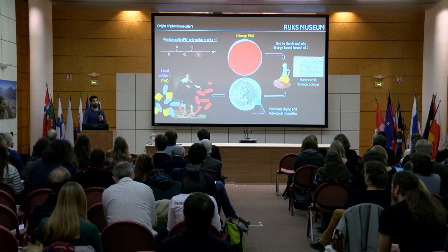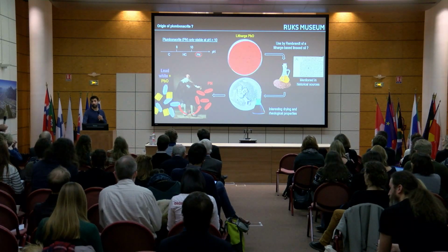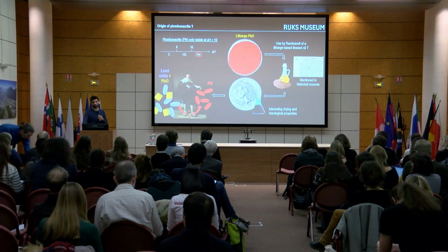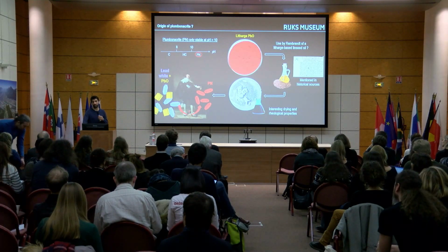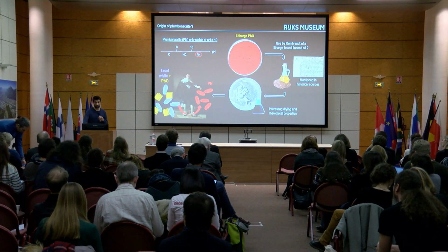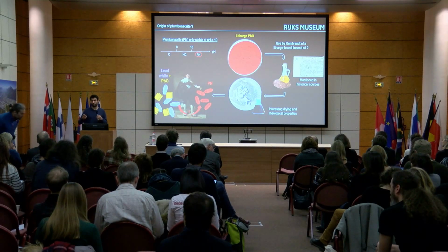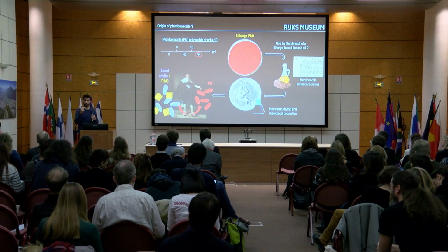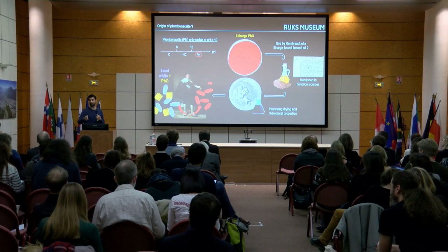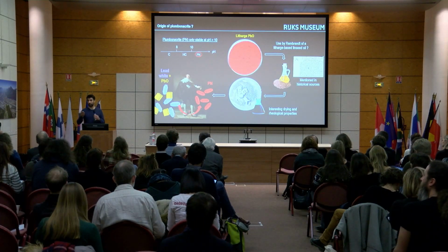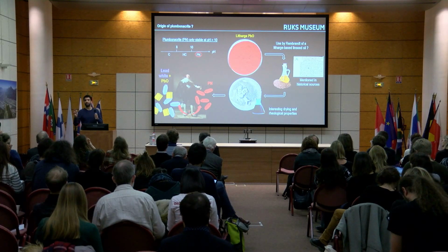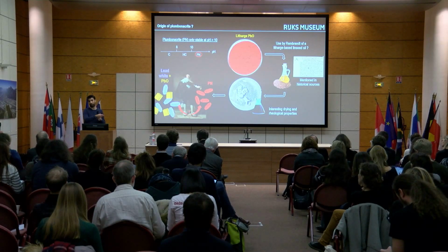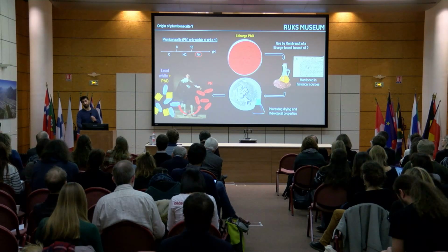Absolutely. So obviously the experiments we did in the lab were with pure litharge, but we do think that a key parameter is if the litharge is entirely dissolved in the oil or not. So according to us, so far it seems that the experiments are showing that you need to have, let's say, still a remaining grain of litharge for this crystallization to kick in and start from this litharge. So indeed, perhaps the preparation method of the litharge could be connected to the dissolving capacities of the litharge in the oil and could be indeed linked to this specific chemical pathway. So this is indeed something very interesting to follow on.